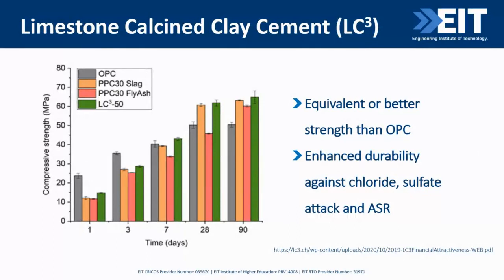In addition, LC3 has higher resistance against chloride ingress compared to ordinary Portland cement, and compared to ordinary Portland cement with 30% of fly ash. LC3 also performs well in tests for sulfate resistance. And there is also a significant improvement of alkali silica reaction mitigation compared to ordinary Portland cement.